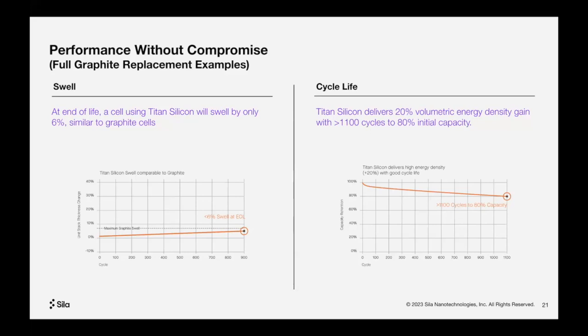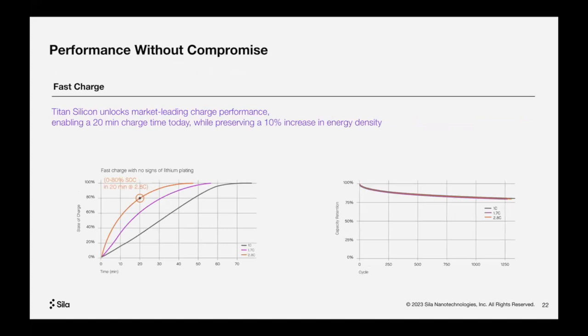And the Titan silicon swells about the same amount as graphite. Graphite generally out to 1,000 cycles is roughly 6, 7, 8% swell, somewhere in that kind of range. And you can see here with our Titan silicon that we're able to keep it below 6% with long cycle life. And you can see on the right the cycle life that comes with that 20% increase in energy density, you're getting over 1,000 cycles in this particular application. The cycle life really is confirmation that we've got swell contained. So these go hand in hand with one another.